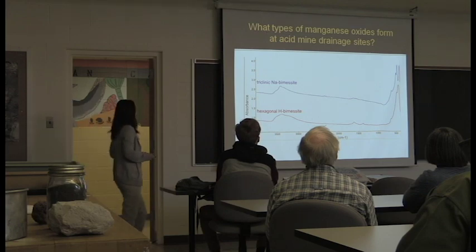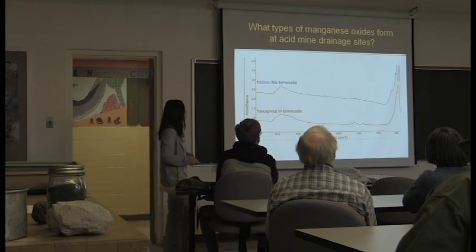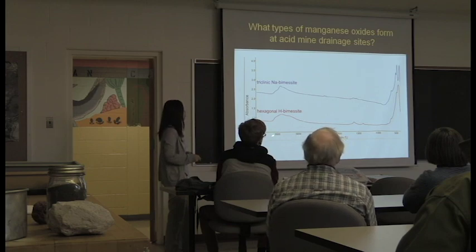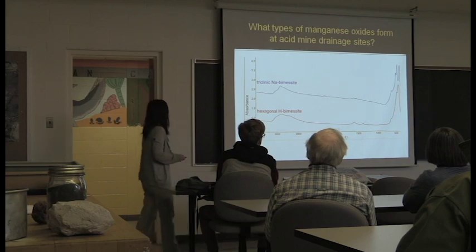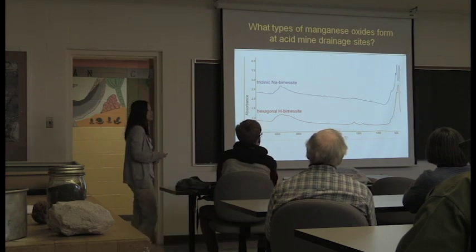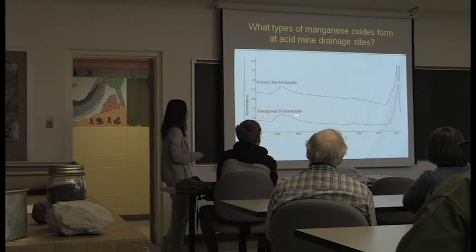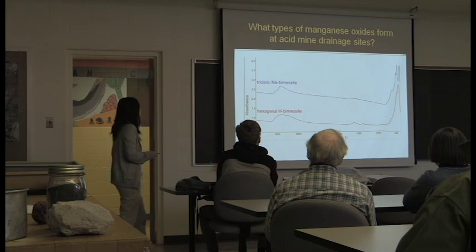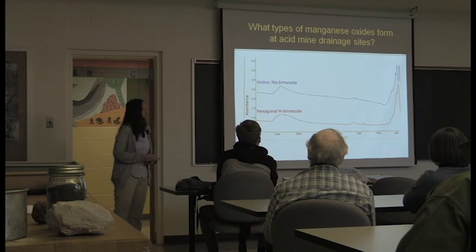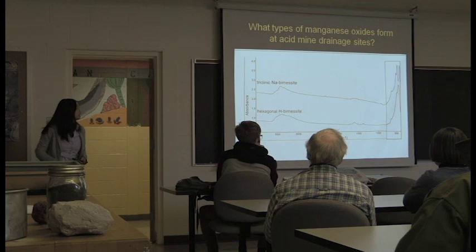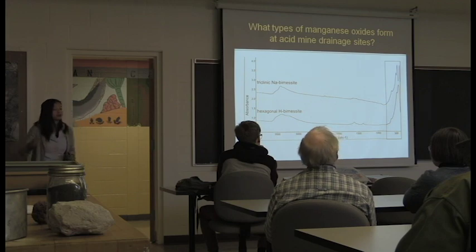But we first needed to figure out whether we can differentiate between triclinic and hexagonal birnessite. These are 2 FTIR patterns. On the x-axis, you have your wave number, or a value for infrared radiation. On the y-axis, you have your absorbance of your IR. And so this is the FTIR pattern for a hexagonal birnessite that was synthetic. And this is for a synthetic triclinic birnessite. Down here, around 3,500 inverse centimeters, these are peaks related to water molecules in your structure. Down here, around 500 inverse centimeters, are peaks that are related to manganese oxygen bond distances. So this is related to that manganese octahedra in our crystal structure.